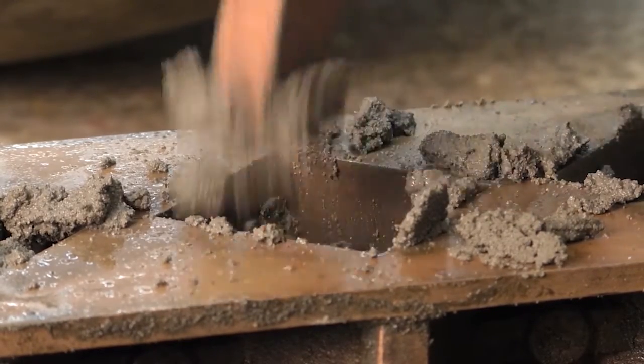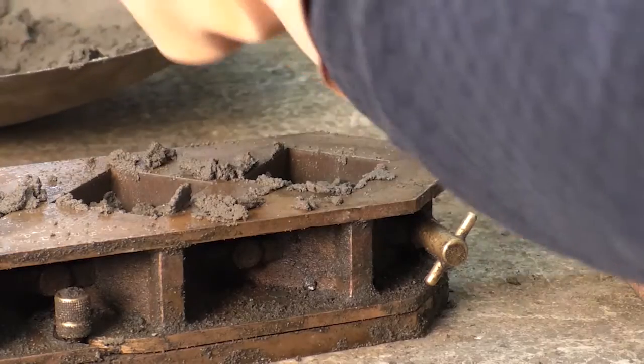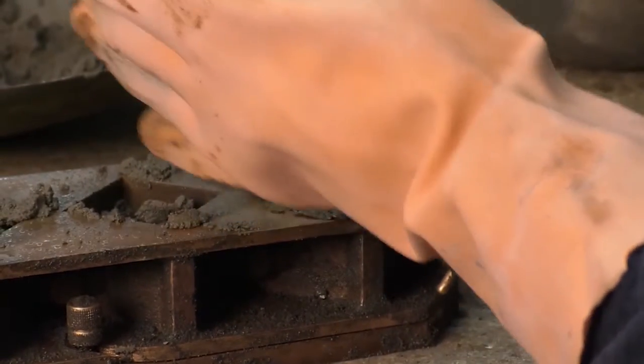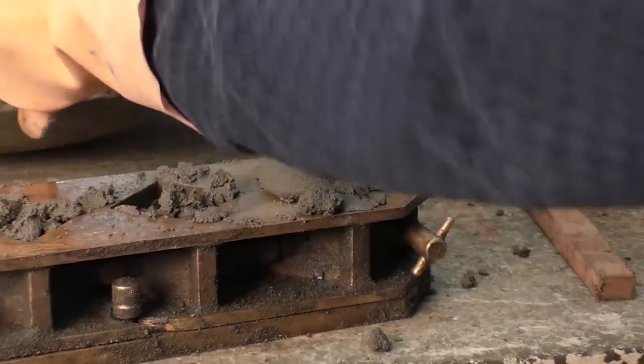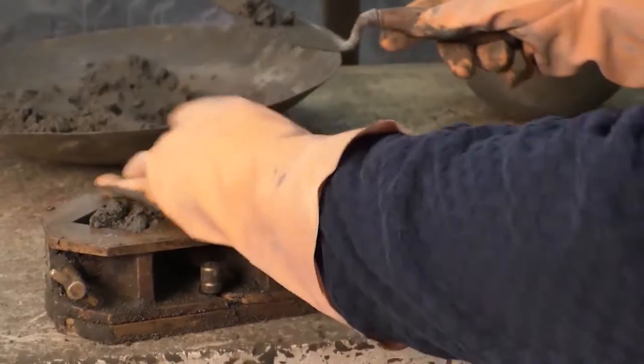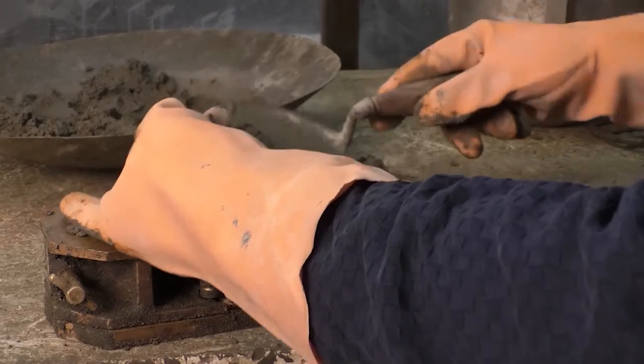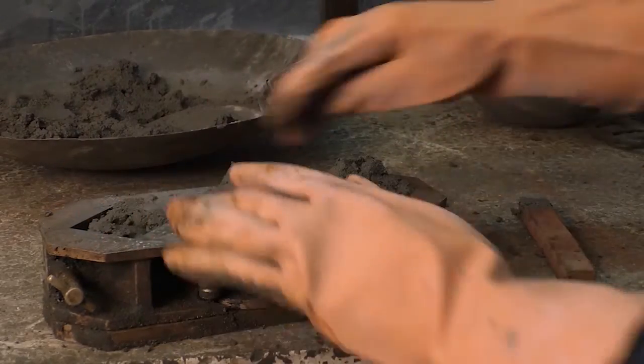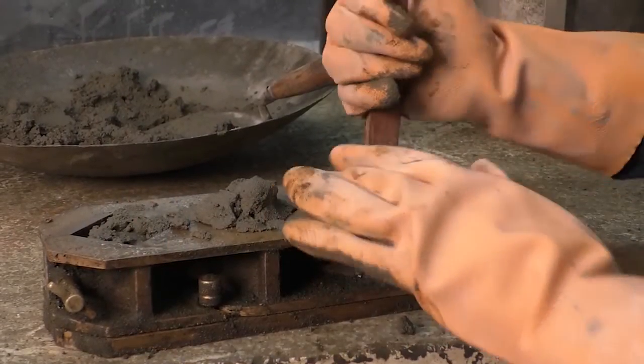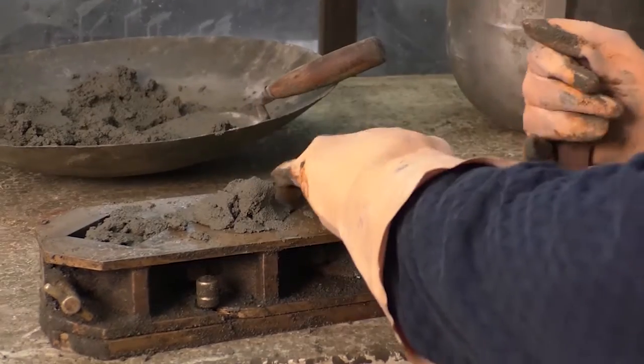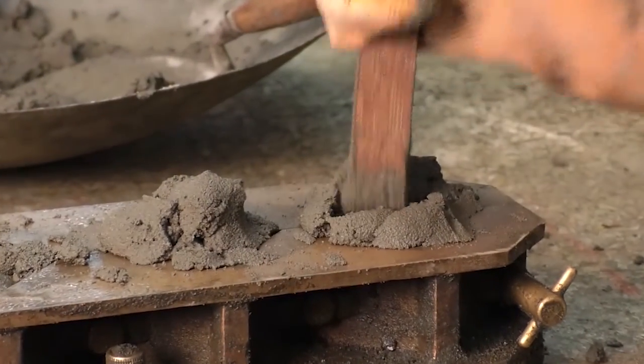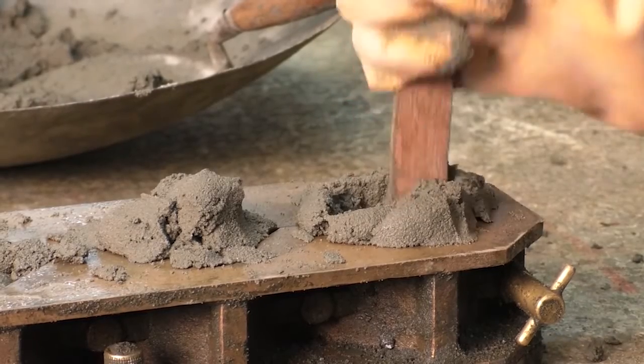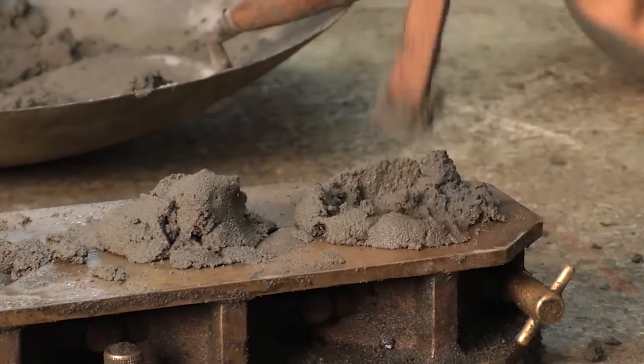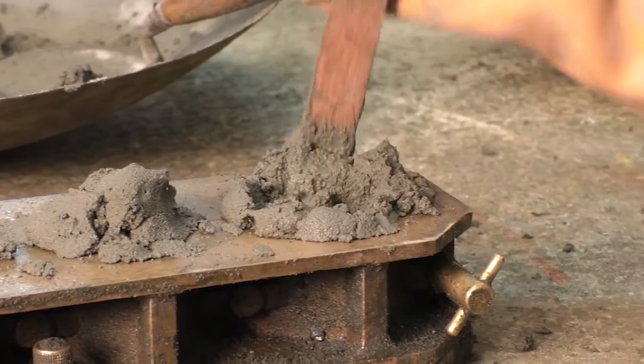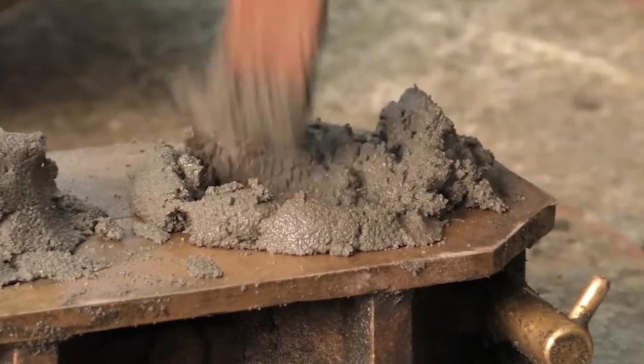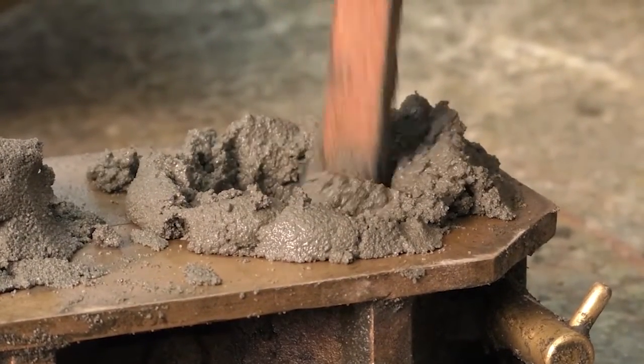When the tamping of the first layer in all of the cube compartments is completed, we have to fill the compartments with the remaining mortar and then tamp as specified for the first layer. During tamping of the second layer, we have to bring in the mortar forced out onto the tops of the molds after each round of tamping with gloved fingers and the tamper, after completion of each round and before starting the next round of tamping.